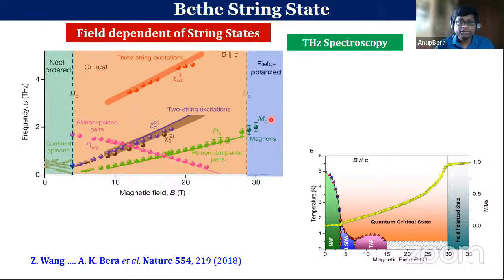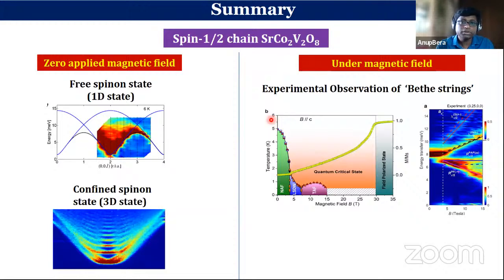So this comes to the summary. I have shown basically 2 quantum phenomena, based on the spin half chain compound. The first one is in zero field, where we observe the spinon, quark-like confinement of the spinons, which is effectively governed by the interchain coupling.